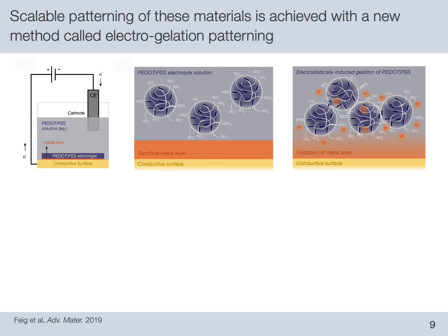Despite these promising properties, for this material to be used in bioelectronic devices, we still needed a more scalable and versatile patterning method than the molding-based fabrication that we had used to develop the material. To achieve this, we developed a new patterning method called electrogelation, which relies on the controlled electrochemical oxidation of a sacrificial metal layer. Oxidizing this layer in the presence of a PEDOT:PSS electrolyte generates metal cations that induce gelation of